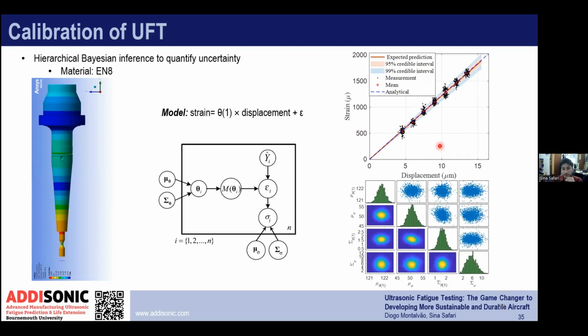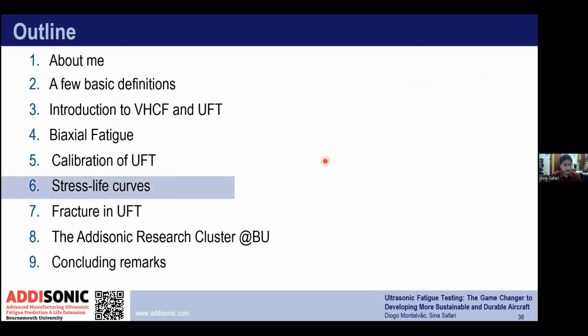If we collect those data for different tip displacements, it gives me the strain for each operational level, and then I can build a relationship between the tip displacement and the strain. The first thing to notice is it's pretty linear, as the data shows a pretty linear trend. And what we can propose is easily just a linear relationship as a model, which shows the strain is correlated with the displacement. So we used a hierarchy of Bayesian inference. I'm not going to elaborate too much on the algorithm, but it just means that if you have multiple data sets, not just one, you can use a hierarchy of regression to find out the uncertainty in the data and distribute it. So that's the whole process.